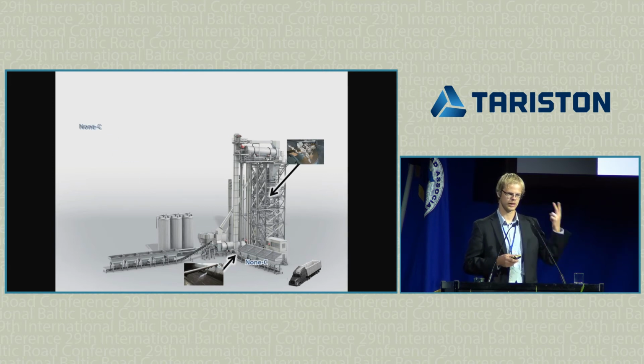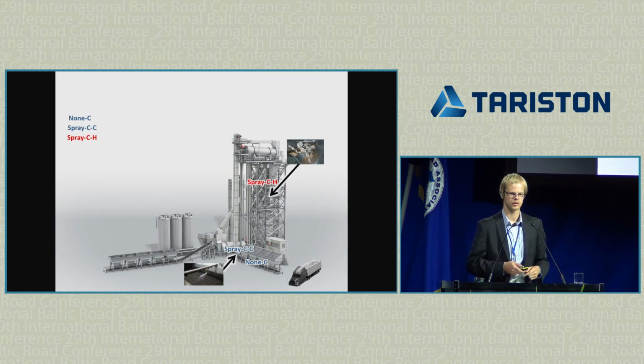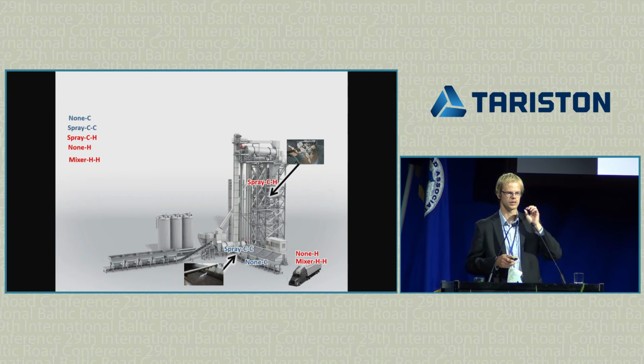Now, we have 2 additional locations, but I actually have five different places to take samples. First of all, I have just a RAP sample. We took it before adding the rejuvenator. Next one, right after addition of the rejuvenator to the cold asphalt. You can see in the letters, it means we sprayed the rejuvenator on a cold reclaimed asphalt, and we sampled the mixture cold. Next, the same sample went through the heating drum, so we sampled it hot. Next, we sampled a reclaimed asphalt that was heated without any rejuvenator. And finally, we had a sample where the rejuvenator was applied hot, and it was sampled hot.